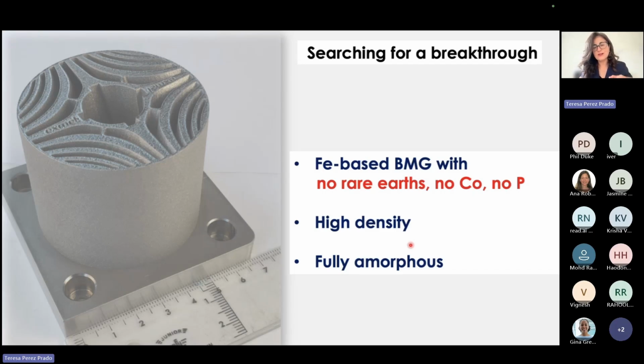Now, this is very, very small. There are other iron-based metallic glasses that can be produced with thicknesses of a couple of millimeters and so on, but these ones, with these compositions, the glass formability is extremely low. And then we not only want to make these complex geometry components with this composition, but we want, of course, high density and a fully amorphous state, so we can really use their excellent magnetic behavior.